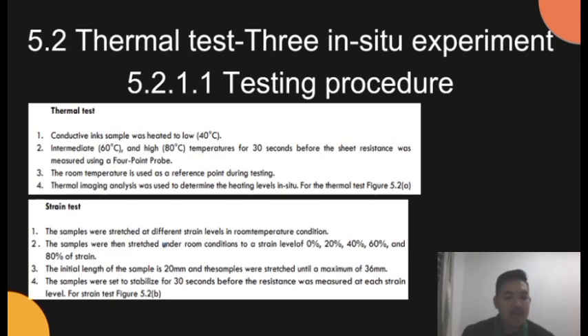First, the sample was stretched at different levels at room temperature, at strain levels of 0%, 20%, 40%, 60%, and the last one is 80% of strain. The initial length of the sample is 20 mm, and the sample was stretched until a maximum of 36 mm. The sample was set to stabilize for 30 seconds before the resistance was measured at each strain level. For the strain test, figure 2b is shown there. Now let's move to the next slide.